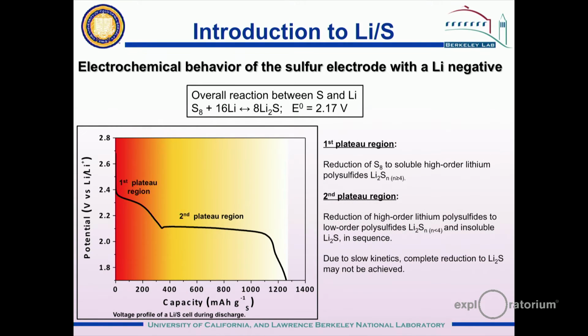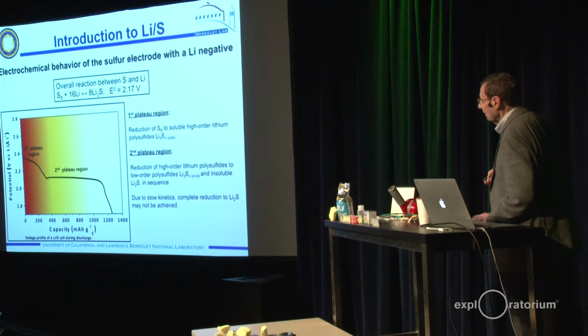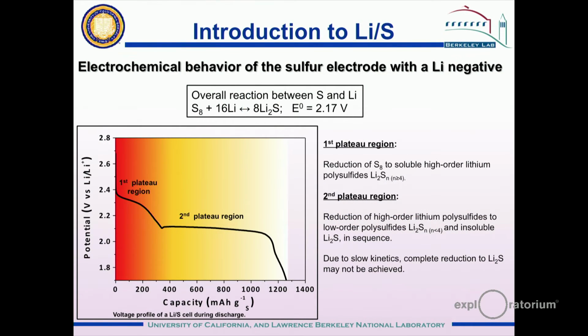So if we build a lithium sulfur cell and we operate it in the laboratory, measuring the voltage of the cell, you can see it's of the order of 2 volts, versus the capacity of the cell, and here we're expressing that in terms of milliamp hours of charge per gram of sulfur in the electrode, we see 2 regions, an upper plateau where the sulfur is reacting with lithium to form lithium polysulfides, and a lower plateau where the sulfur and the lithium polysulfides react with more lithium to form Li2S. And this is the overall cell reaction up here. And the average cell voltage is about 2.17 volts. So that's what's happening inside the lithium sulfur cell as we operate it.